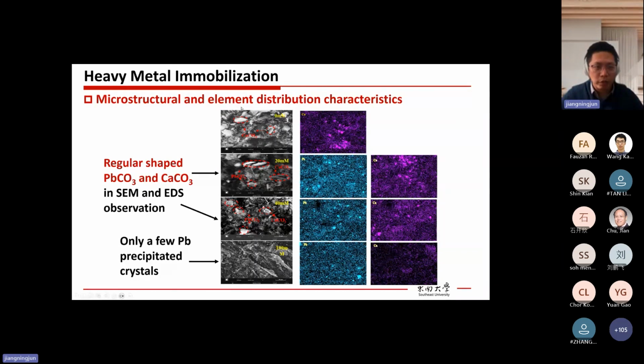So in this one, the first graph shows the no contaminant case. We can see calcium carbonate, and from the EDS scanning graph, we could also spot these various bright points. They represent crystals in soil. Then for low lead concentration case, we could see both calcium carbonate and the lead carbonate.